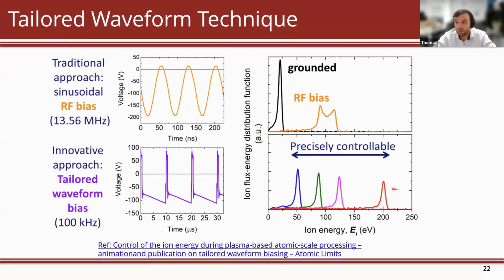So here are just some examples. Here you have a traditional approach, the 13.56 megahertz, and you see this oscillation. So you go up to the plasma potential, so you're slightly positive sometimes, but most of the time you're negative. You get a large negative average. Grounded, this is showing the plasma potential, basically. And then when an RF bias is applied, you get a split peak. But if you use a tailored waveform, so for example, this shape here, you can get these really narrow distributions, okay? And you can have very precise ion energy control simply by changing the voltage here. So there's a direct link between what voltage you get here and what energy you get here, okay?